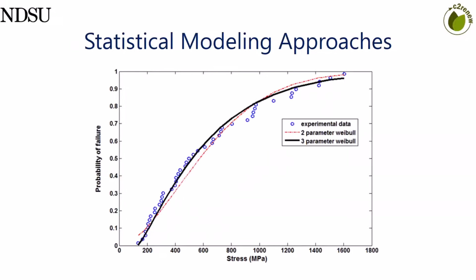We've also found that due to the variability of a lot of these natural fibers, especially when we start putting them into composites, the utilization of a statistical modeling approach such as Weibull is somewhat effective. Much like one can assess the strength and the performance of ceramics that have a lot of porosity and a lot of variability in the performance due to the porosity, we've used that same approach with natural fibers, and with fairly good success in terms of being able to predict that performance due to the variability of the fiber structure itself.